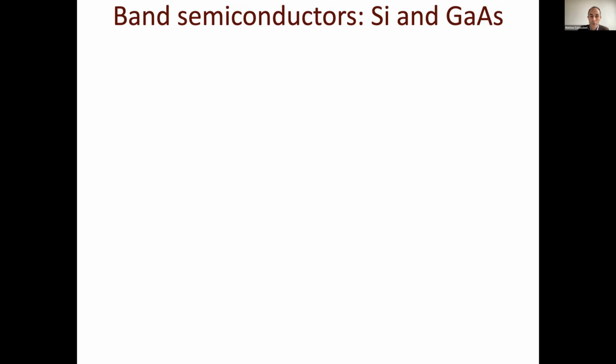Why should one want to use Hubbard correction on silicon and gallium arsenide, which are not notably correlated materials or strongly localized materials? It's precisely because of what Nicola Marzari was saying yesterday: this +U correction does, in a sense, the same job as hybrid functionals, aiming at the correction of the spurious self-interaction, since we still have an approximate exchange-correlation functional.